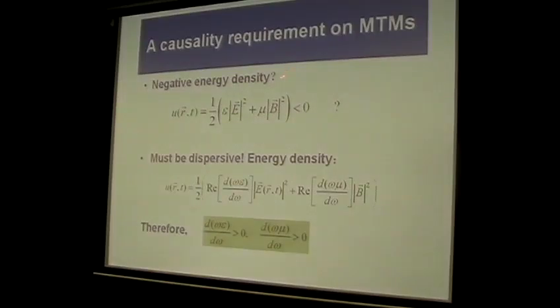Now you may ask the question that if both epsilon and mu are negative, then something will be wrong, because if you look at the energy density, you will find that energy density will be negative. So is that wrong? That's not wrong, because this equation is only for non-dispersive media. For dispersive media, the energy density should be related as this. And therefore, if both epsilon and mu are negative, and if this equation is still satisfied, the energy density can still be positive.